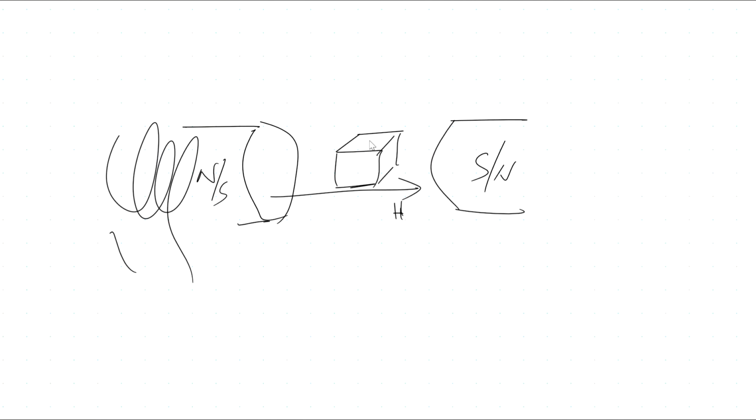And then you can measure a hysteresis loop. So you take this axis, you measure the hysteresis loop, and you rotate around that axis. You also can rotate about this axis, but it doesn't give us much. This axis doesn't give anything because this axis is aligned along the magnetic field. So there is nothing that we change if you rotate about this axis. But there is also that axis, and you can rotate about that axis. And by rotating it and measuring magnetization along different directions, you can see how different the hysteresis curves are.